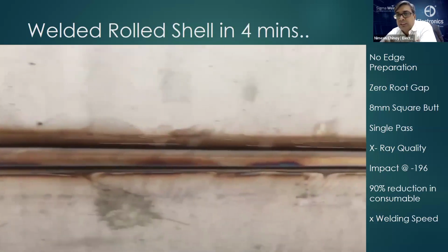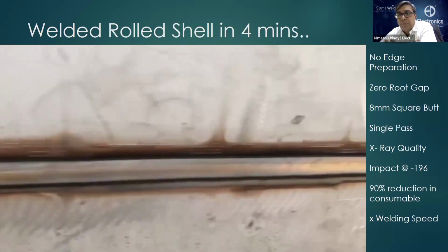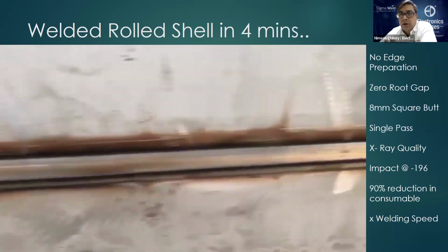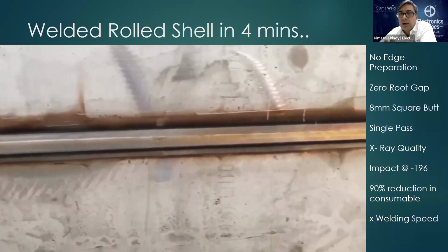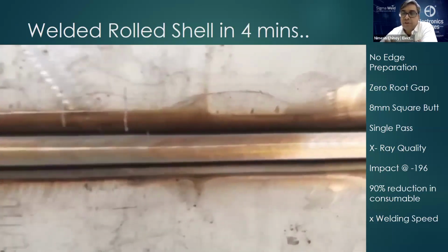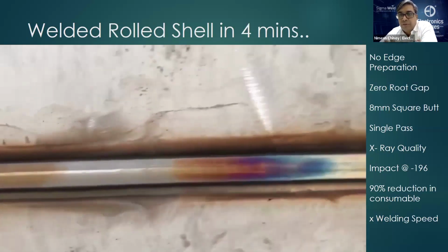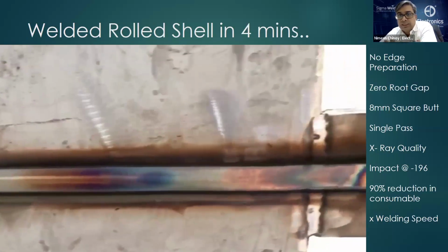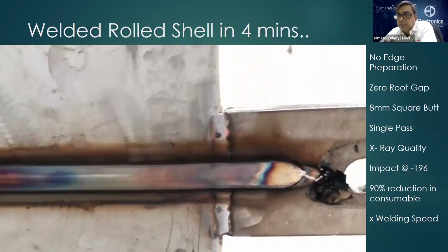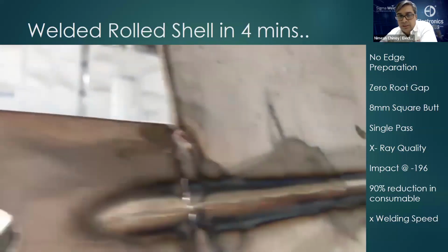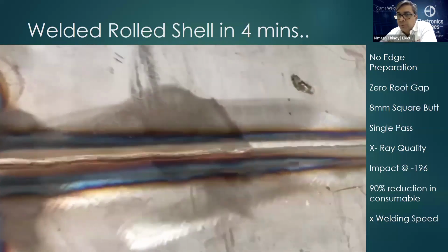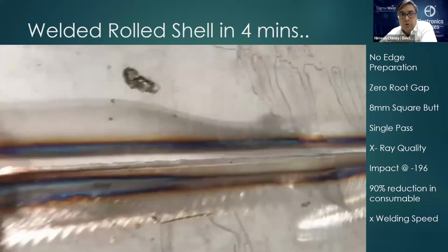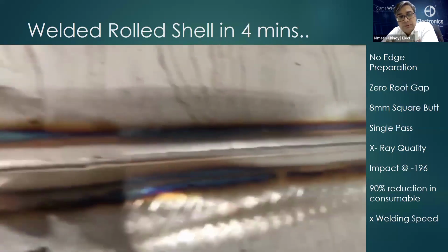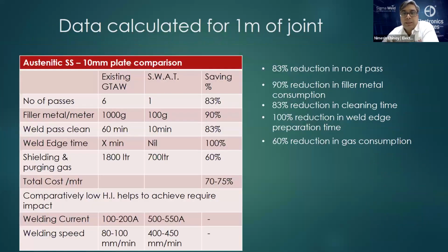Typically, if you were doing this process manually, it was a one shift job, that is an 8-hour job. And on automation, it takes close to about 1 hour to do this, or at least half an hour with setup time and all. We've reduced the time for our customer to less than 4 minutes, and it's a 90% reduction in consumable, and it's an impact minus 196 tested joint. So it's very high quality, no root pass required, no edge preparation required, and a single pass welding.